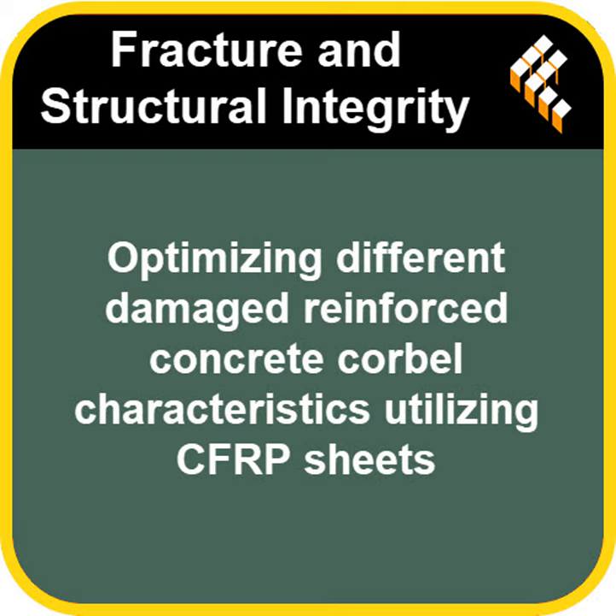Okay, so the results. What did they find? Let's start with the ultimate load. How much weight could they handle? This is where it gets interesting. The undamaged corbels that were strengthened with CFRP showed a really significant boost. How significant? A 19.72% increase in ultimate load compared to the control specimen. That's going from 710 kilonewtons for the control up to 850 kN for the strengthened ones.